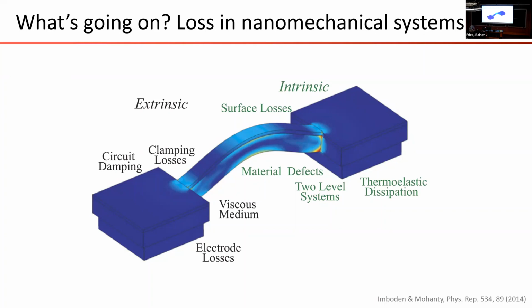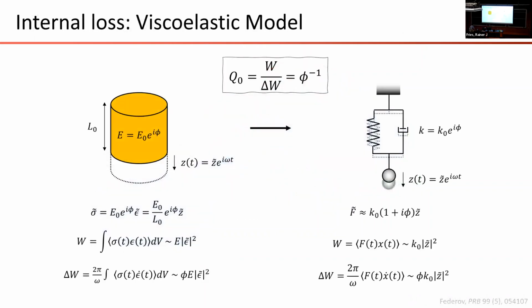Now, we often think of two-level system type defects in material giving rise to internal friction. And for these high aspect ratio devices, it turns out that intrinsic losses dominate. We don't really understand the microscopic origin very well. We just know that we can model the loss mechanism as intrinsic in origin, acting like an internal friction. So how do we typically model that? We model that with viscoelasticity, which basically says that the stress produced by straining an elastic body is slightly time delayed, which gives rise to essentially a viscous interaction that produces loss.